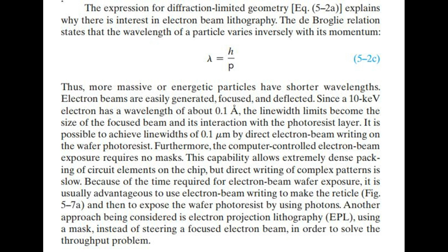It is possible to achieve line widths of 0.1 μm by direct electron beam writing on the wafer photoresist. Furthermore, the computer-controlled electron beam exposure requires no masks. This capability allows extremely dense packing of circuit elements on the chip, but direct writing of complex patterns is slow. Because of the time required for electron beam wafer exposure, it is usually advantageous to use electron beam writing to